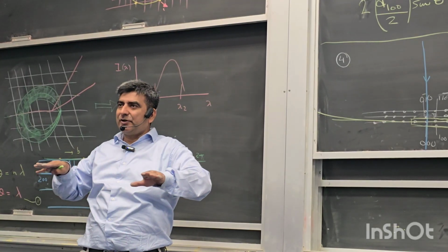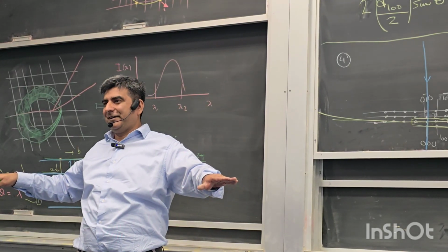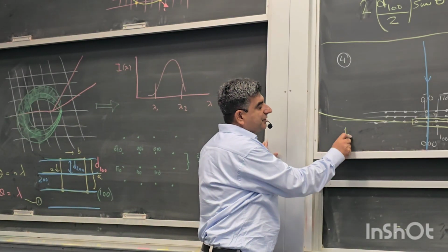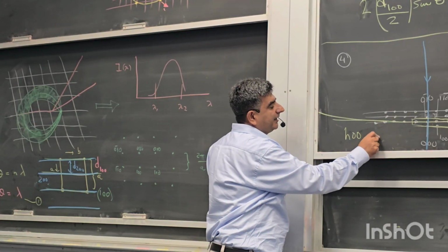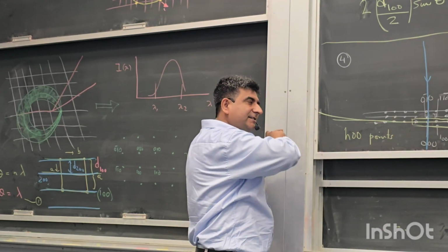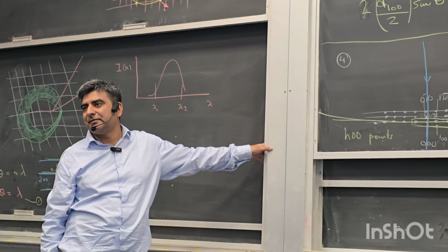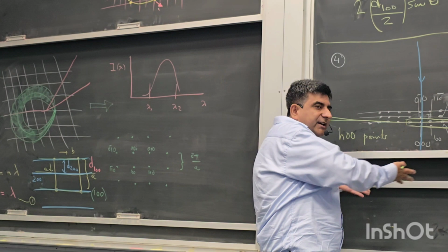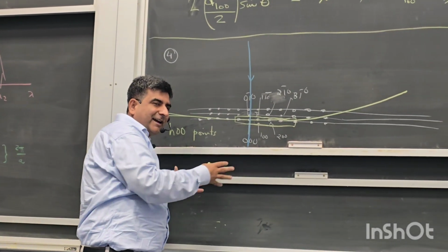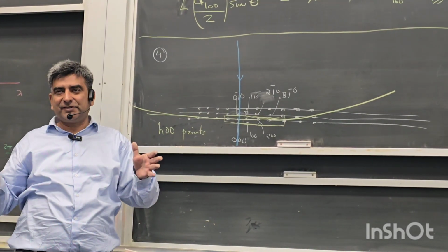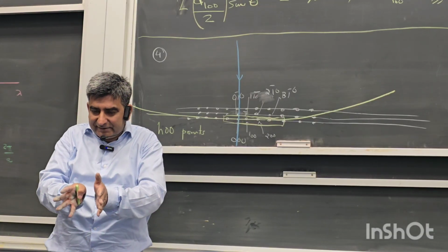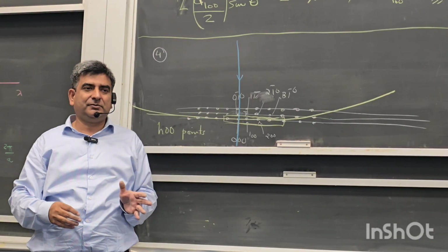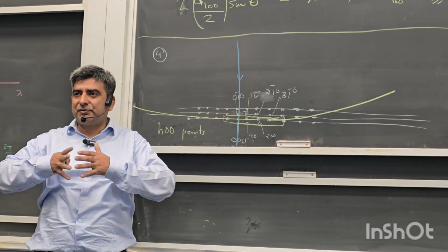So all of these points on a row will lie on the Ewald sphere. These points are all H00 points in a row, not even a net, it's just one row of the reciprocal space. So all of these points will give scattered radiation. If I have some kind of detector placed at the bottom, and I also have a magnification for the electrons, so the electrons are coming at small angles, and I want to do some kind of magnification for electrons, so I put an electron microscope which can magnify electrons through different kinds of lenses.